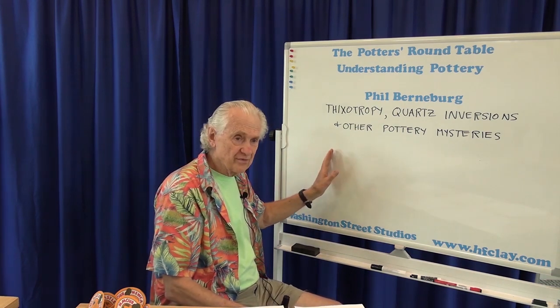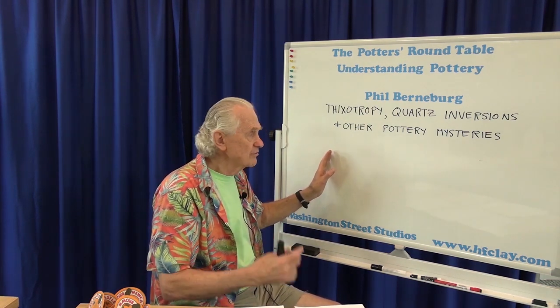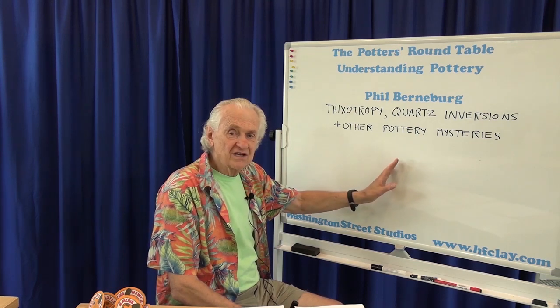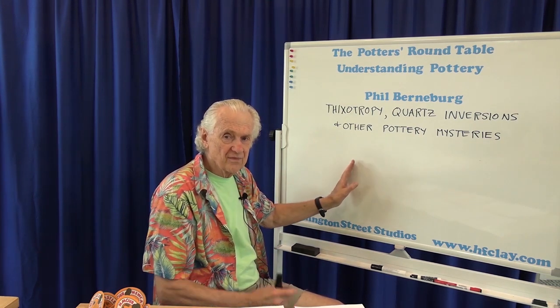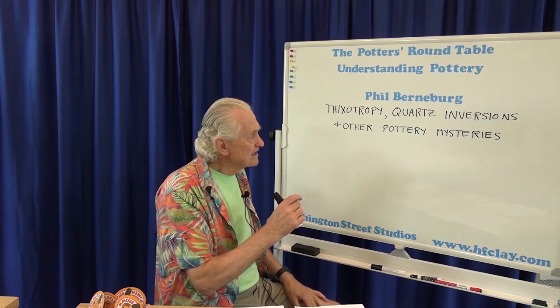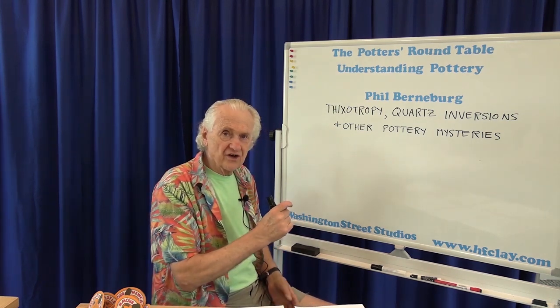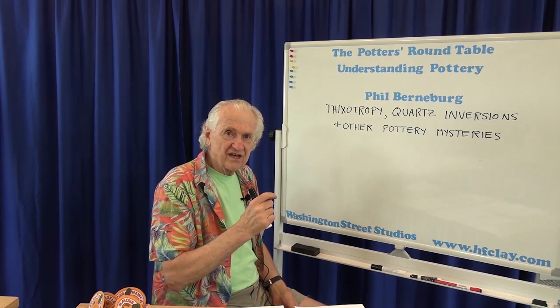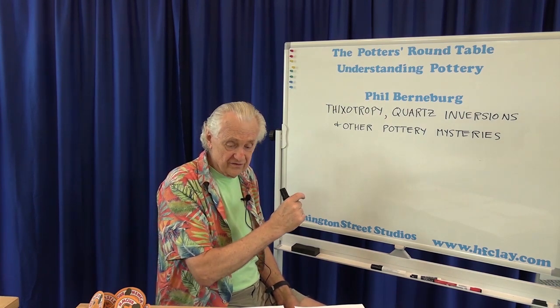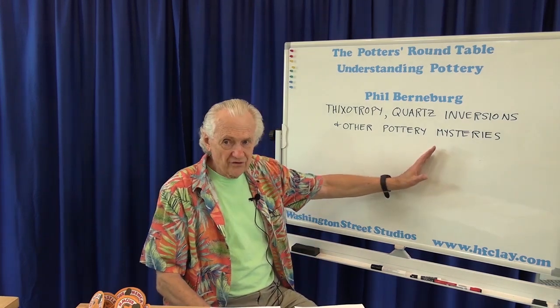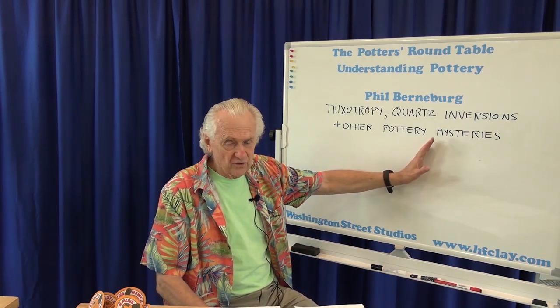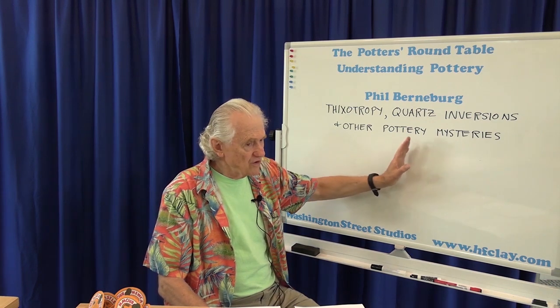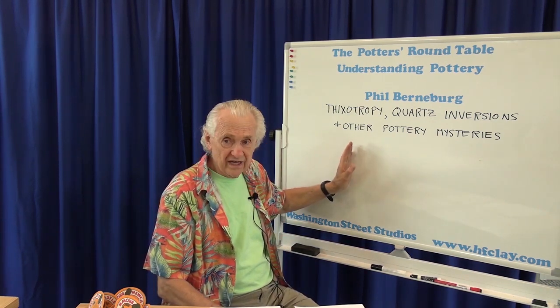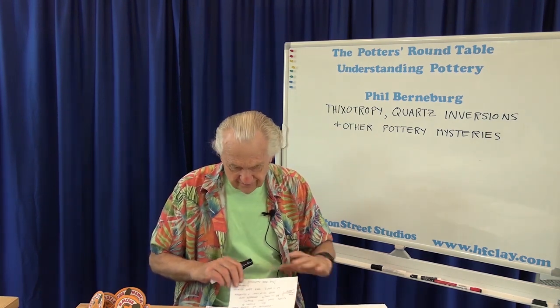So when I get to a lower temperature, around 500 degrees in round numbers, Fahrenheit, the cristobalite changes from the high form to the low form, and it contracts a little bit. And because of the slight differences in the structure, when the cristobalite contracts, it contracts more than the quartz does, just as a side point. So coming back down, I went through the quartz inversion, and then I went through the cristobalite inversion. Altogether, these are called the silica inversions, okay?